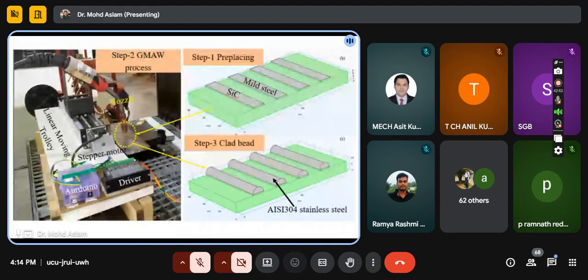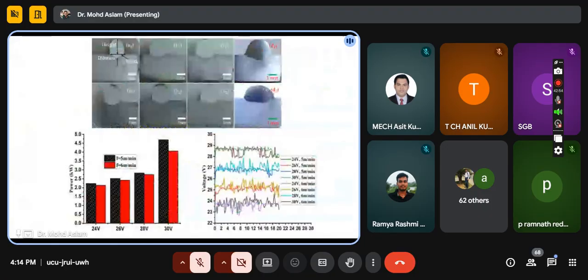After that, you can clearly see less dilution, but it developed end-to-end dilution and proper metallurgical bonding. That's why the incomplete fusion problem was solved, compared to the previous one that had lower wear resistance and corrosion resistance. Now we are using silicon carbide. Silicon carbide is very hard compared to steel. So here hardness improves, corrosion resistance improves, as well as wear resistance.